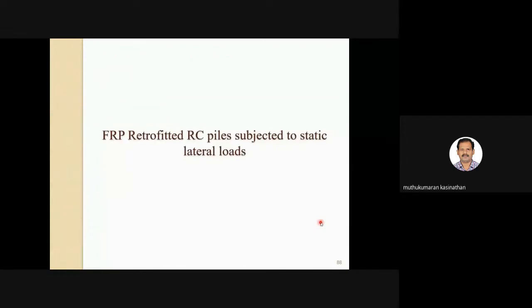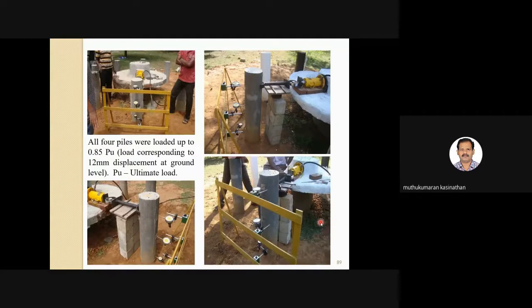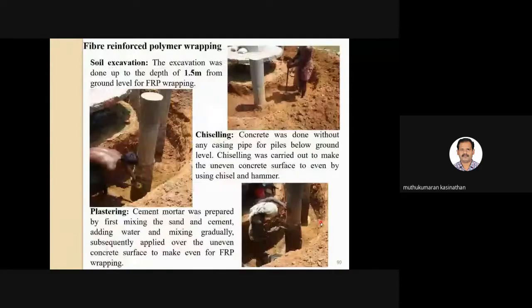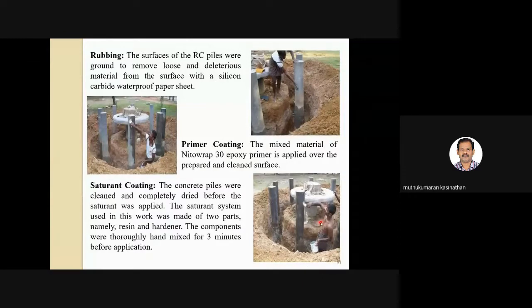Then so far we were talking about the strengthening. We have also gone to the retrofitting. So retrofitting was done where the piles were subjected to almost 85% of the ultimate load. The ultimate load we have theoretically estimated, and that theoretically estimated 85% of the ultimate load has been applied on the pile. So to some extent we failed the pile, close to 85% of the ultimate load. Then the wrapping was done, then the test was conducted. You can see here all these piles were already subjected to 85% of the ultimate load, so close to failure. Then again the same process has been repeated.